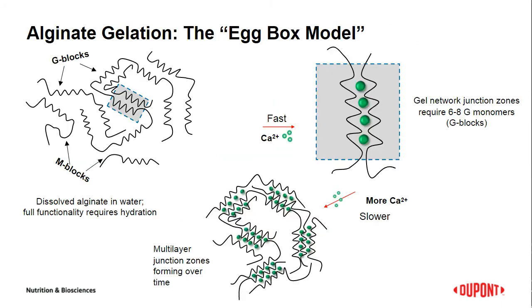In order to achieve the full functionality of the alginate, the product needs to be hydrated in water. This normally requires high shear treatment to prevent clumping. When hydrating the polymer, the viscosity of the solution is enhanced. M blocks in the polymer chain form random coil structures in solution. The G blocks instead show the buckled chain elements which are able to incorporate calcium ions.